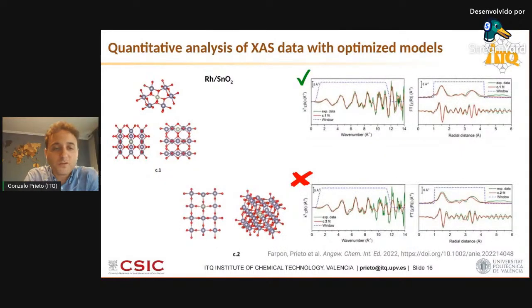So what we do is to generate, using periodic DFT, different site models, trying to probe different local coordination environments for the metal center we are interested in. In this case, it is rhodium on tin oxide. We can generate it for a rhodium isomorphically substituted on different tin oxide facets. We can also model rhodium in subsurface position, so that has migrated into the bulk and so on. And we can then generate all the scattering data for all the scattering paths from the models and do fittings to our experimental data.